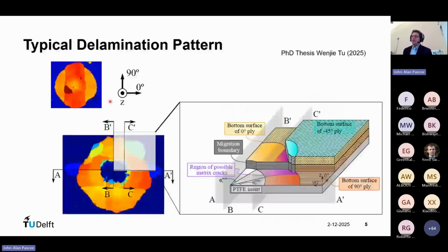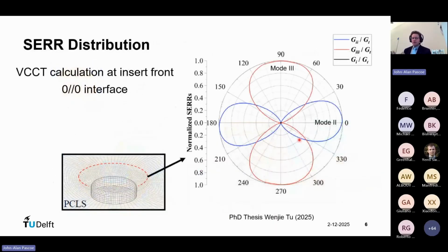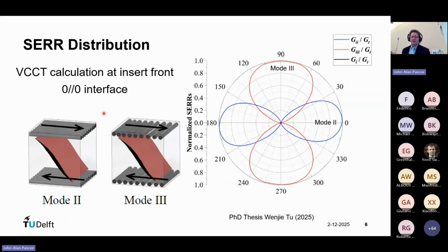And then also, if you notice, the growth is a little bit slower in those directions, right? So that matrix cracking may be somewhat toughening the material or the specimen. We can argue a bit about material properties and so on. Here, just again illustrating. So if you have this mode 2 condition, then the crack migration is blocked by the upper fibers, whereas in mode 3, the crack can continue growing in between the fibers and migrate to the next plane.